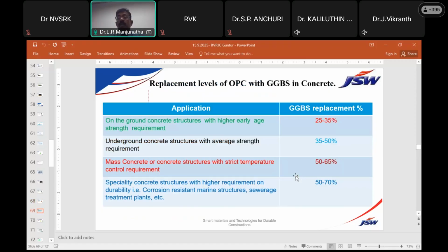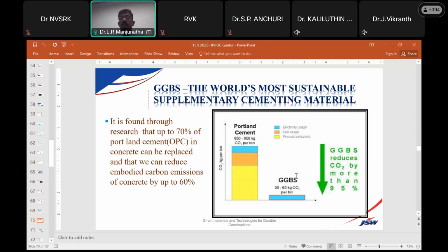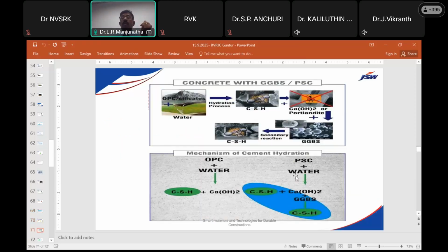The replacement levels are based on the application, we start from 25% up to 70%. So based on early requirement of strength, we can go up to 35% like precast elements or post-tensioning concrete applications, and we can go up to 70% for marine structures, sewage treatment plants, and corrosion-resistant structures. So the advantage of using slag is that already it has suffered emissions during steel manufacturing. Only we have the grinding emissions. That is only about 60 kg per every ton of GGBS, where Portland OPC cement comes with 850 kg emissions. So by replacing that, we can really bring down the emissions in the concrete, either in the manufacturing of cement or in the manufacturing of concrete at the RMC batching plant.